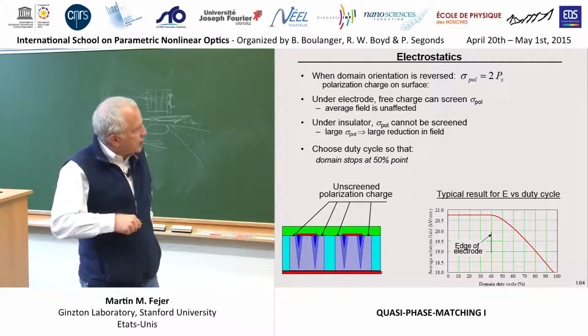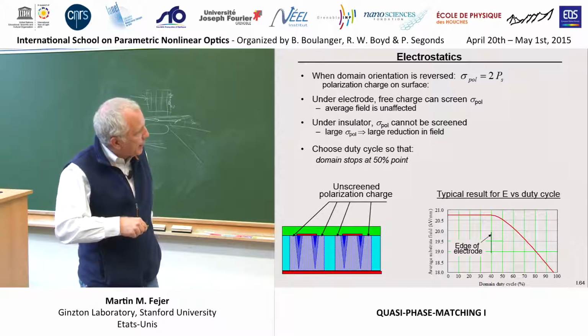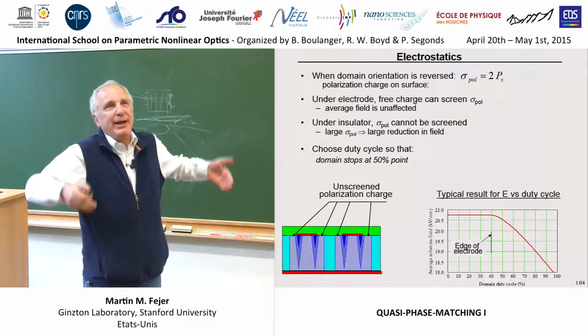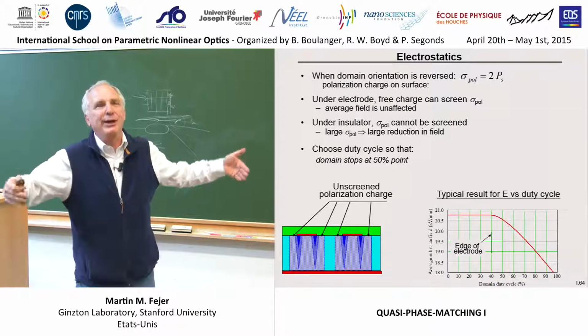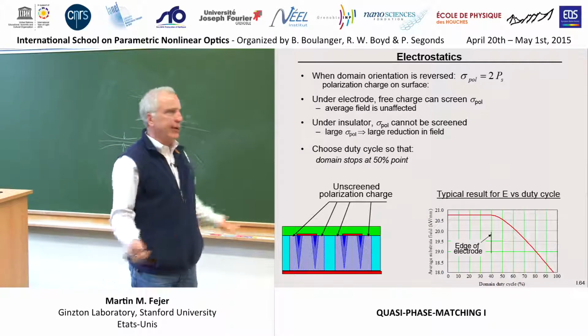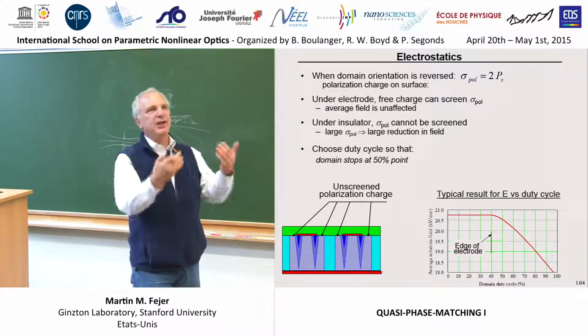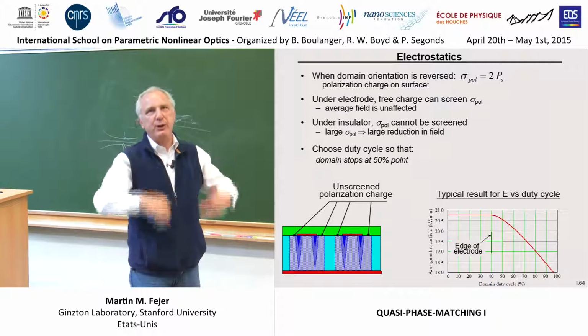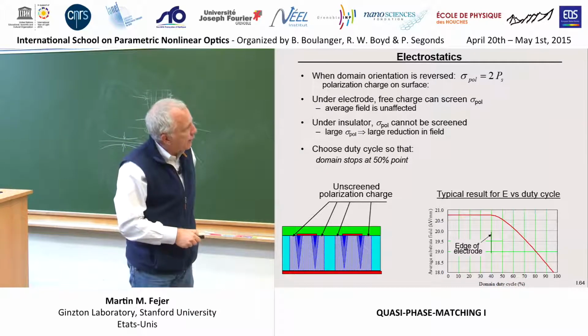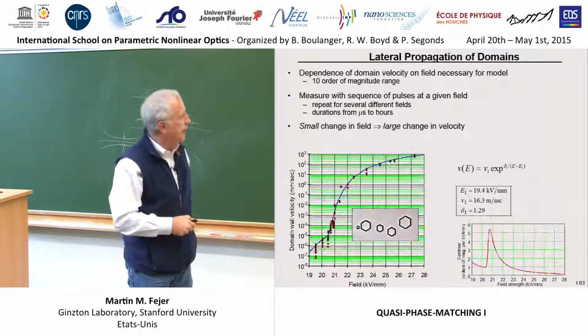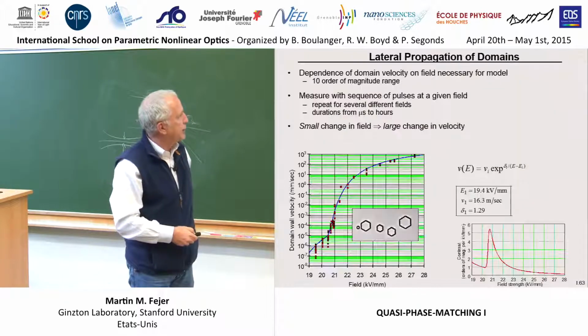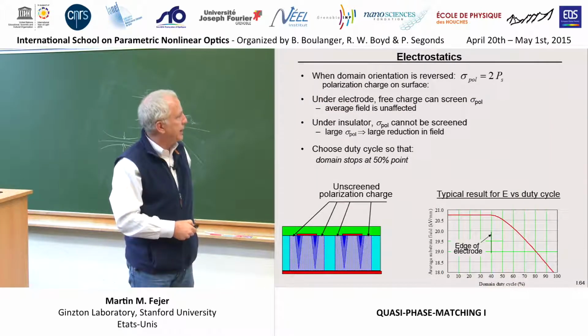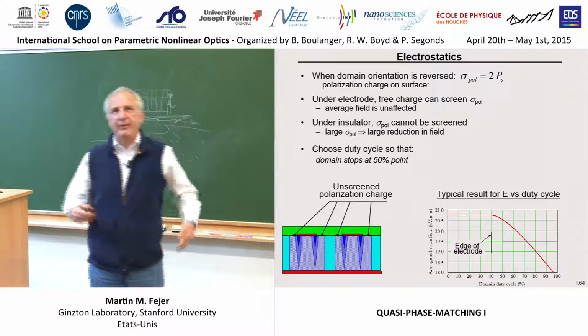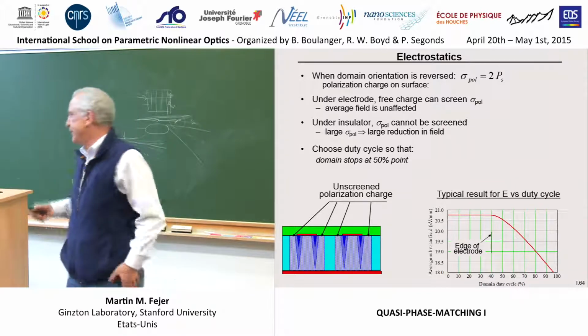So as the domains spread out from underneath this electrode edge, they stop. They self-brake because they make a field that says slow down, and the slope of the velocity versus field is so large that it doesn't have to go very far past the edge before, for all intents and purposes, they stop. 5 orders of magnitude is a large difference in velocity.